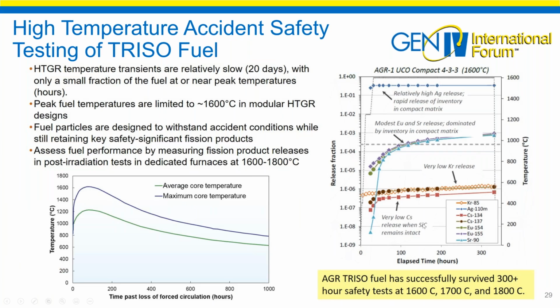Now, high temperature safety testing of the fuel is important because we want to see that irradiated fuel will perform well in the peak accident. I mentioned this total loss of forced circulation, this DLOFC event. And the maximum core temperature just skirts a little bit above 1600 degrees Celsius. That's the maximum core temperature. The average is a little lower. But you'll notice this is in hours. So it takes hours or basically days to reach this temperature. So the operators wouldn't just walk away, but it's passively designed. And it's not even close to the rapid temperatures that you would see in a light water reactor event.